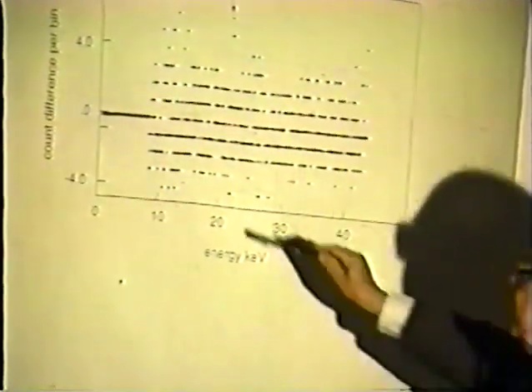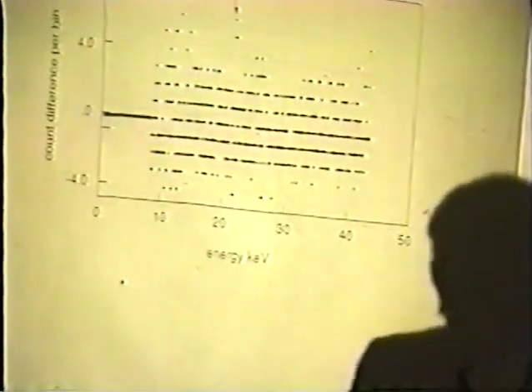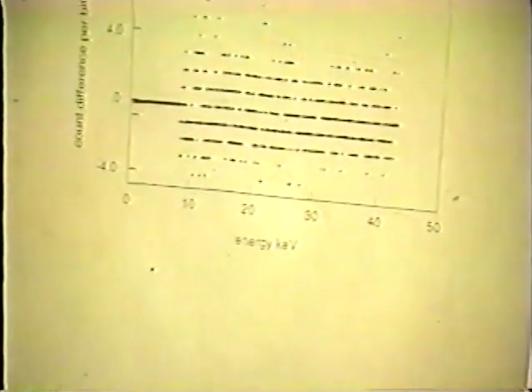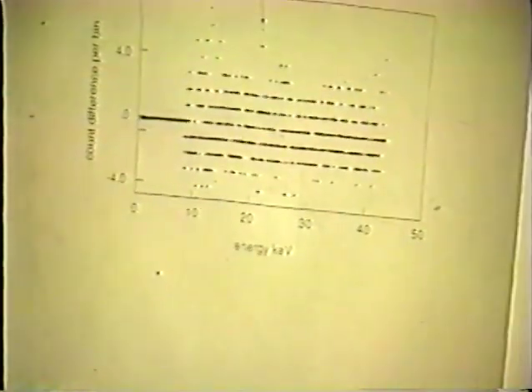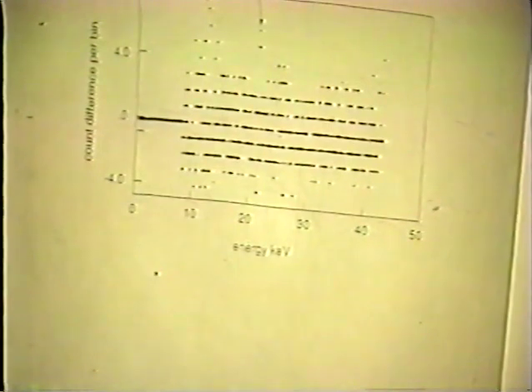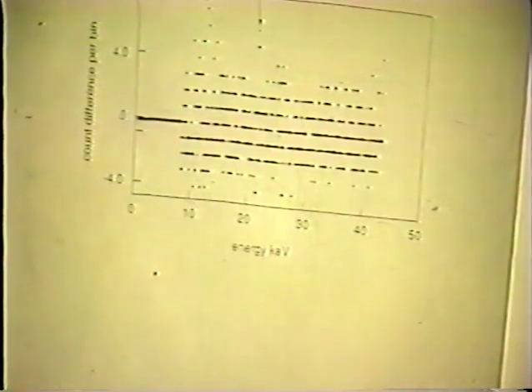And here again, we see another one. And that was one of the puzzling ones because we didn't know what to assign it to. And finally, one of the referees suggested, well, that might be platinum L series. And in fact, remember our counter electrode is platinum. Working in chloride solution, the chances are very good that indeed it will be transferred, and you'll see that. Well, so far, so good.